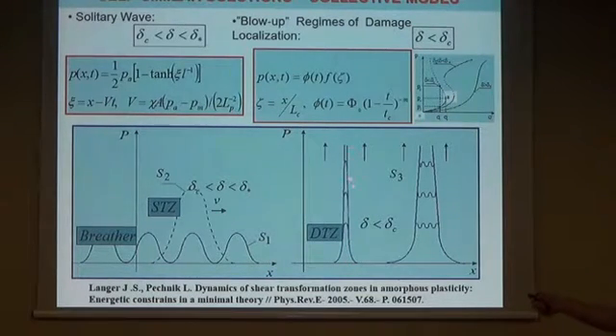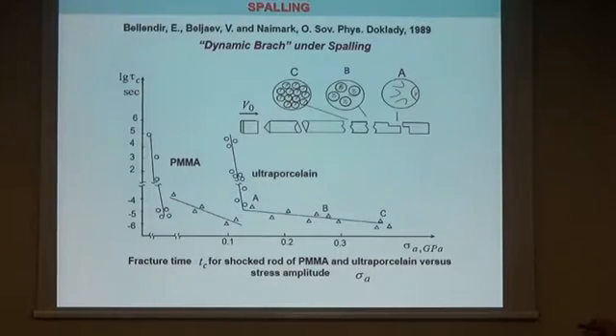It was very interesting that when we established this characteristic type of blow-up modes, ten years later similar results were obtained by Jim Langer from the Kavli Institute of Theoretical Physics, and he named these collective modes damage transformation zones. Our publication on this type of collective modes was in 1989, especially made to explain the specific self-similarity feature due to shock-wave loading of PMMA or ceramic samples, which produced a very specific image of fracture surface with numerous mirror zones.